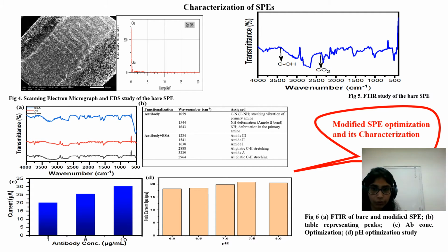Further, the screen printed electrodes modified for immunosensor fabrication were also characterized using FTIR. Figure 6A and B represent the FTIR spectra in which the peaks obtained are characteristic of the amide bond, CN bond and primary amines, which confirms that the antibodies and BSA are attached to the electrode surface. Further, antibody concentration optimization was also done, in which it is clearly shown that 10 microgram per ml shows the highest peak current. Therefore, it is considered the optimum value for immunosensor fabrication. Also, the pH optimization study was done, in which pH 7.4 shows the highest peak current, which was considered the optimum pH value for experimentation, and it is also a physiological pH.